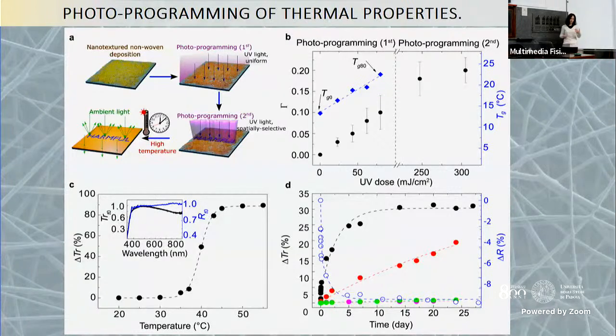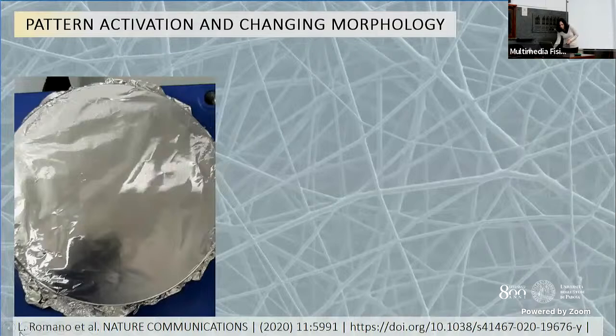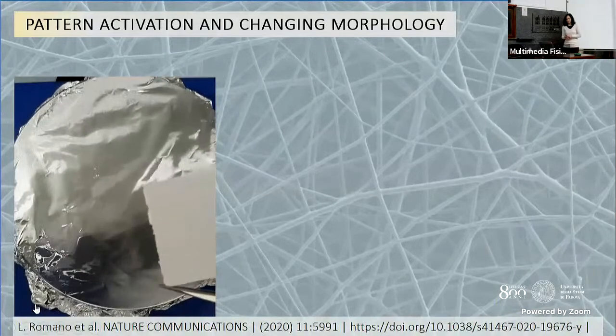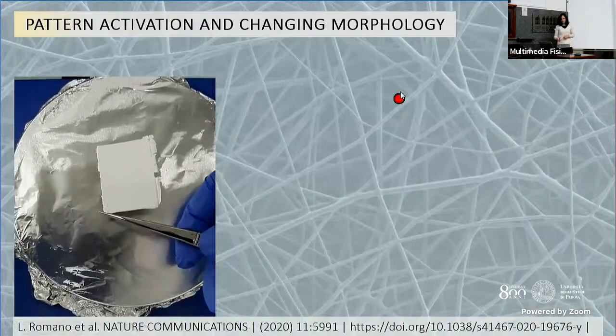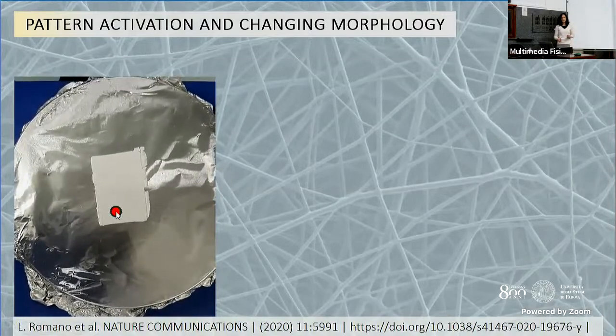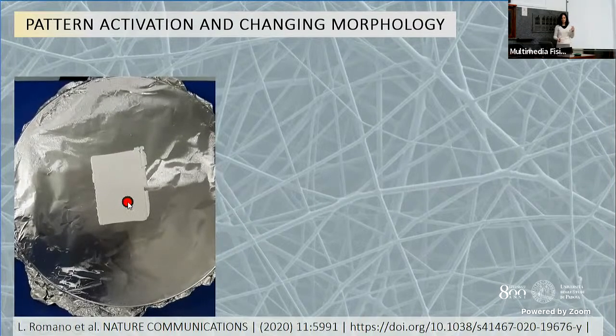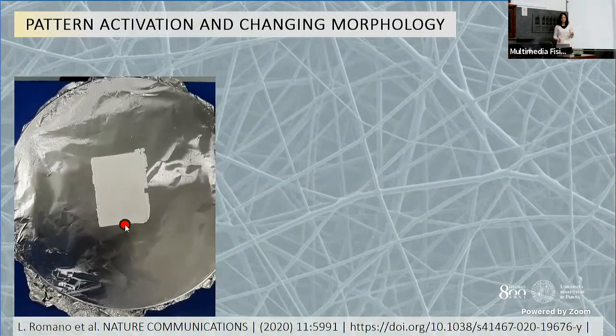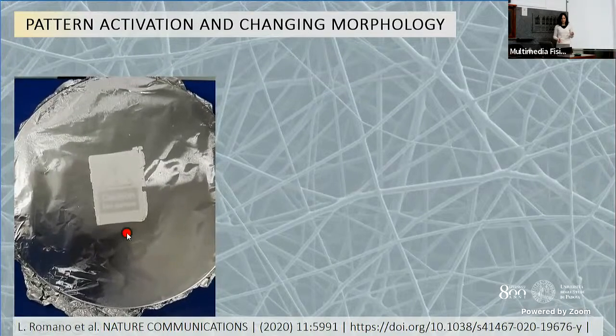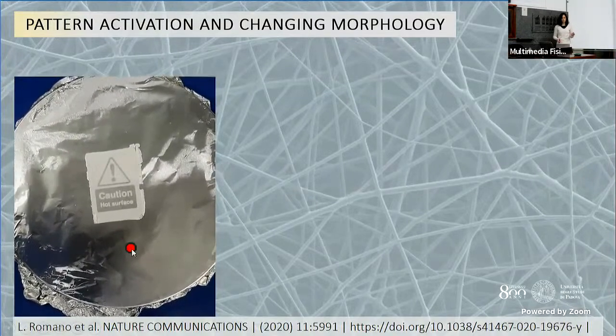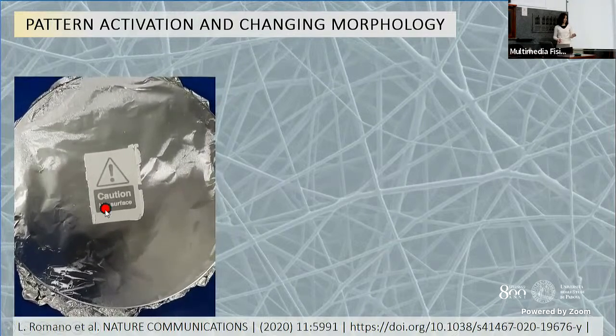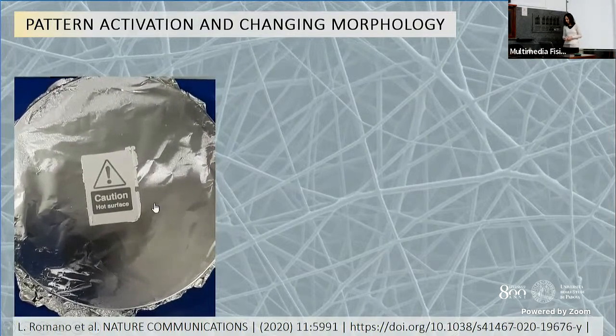We studied how transmission and reflection change for exposure at different doses and for longer periods, as you can see, for several days. And just to try to make it clearer, this is a sample of nanofibers on a substrate. We did the two photoprogramming steps, and we put the sample at 55 Celsius degrees. And you see that the message that was encoded is now clear, but it was not before, okay?